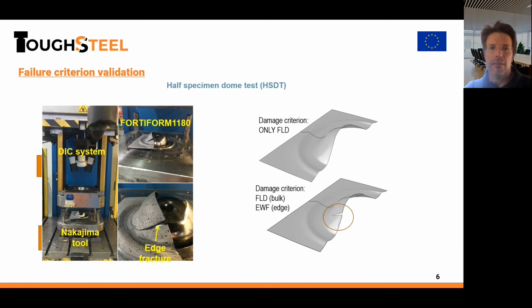Now I can show the real cases that we use for the model validation. Here you can see the half specimen dome test. In this case, you can see how with our model, with the essential work of fracture, we can catch the fractures in the edges. And when we use only the FLD, we can see this type of failure, and we can't see any cracks in the edges.